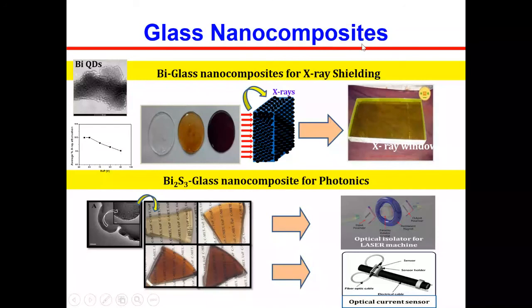This glass composite is another spin-off application. I told you that glass can be used instead of lead. We use bismuth nanoparticles, only 0.5% nanoparticles in it, and it shows 100% X-ray absorption. We made a US patent out of it. When we have bismuth sulfide quantum dots in the glasses, these glasses show magneto-optical properties. So instead of garnet, we can use these glasses in magneto-optical applications. These are the spin-off applications we found in photonics.